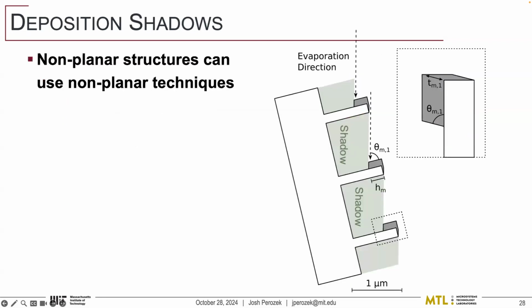So the first thing we notice is that we have very non-planar structures, so we don't need to use the planar processing techniques that have been dominant in the silicon industry for so long. And one of the first ones we looked at was, what if we just tilt the sample? So if you take your fin array, this is a very simplified sketch of the fin array, and you tilt it and have a directional deposition, so think snow falling down on a surface at an angle, those fins start to form shadows. And those shadows prevent any material from depositing there, and you can start to pattern things along the top of your fins instead of the bottom of your fins.